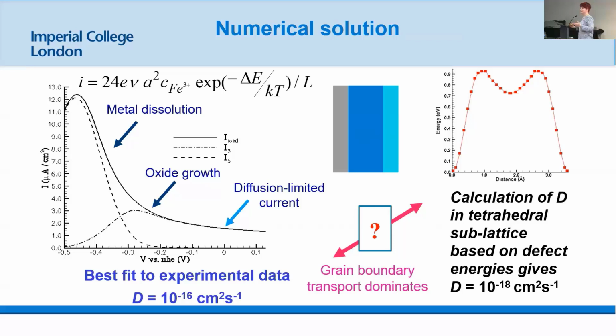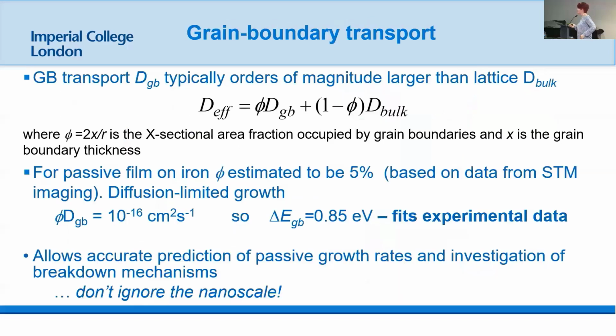So what that is telling us, actually, is that in the growth of these passive films, at least on iron and ferrous alloys, the current density in the passive state, the growth rate, is massively dependent on the grain boundaries. Right? Grain boundary transport, which you can then, this is a little bit more hand-wavy, but you can extract from the images the percentage of areas that contribute to those grain boundaries. And when you then fit diffusion through the grain boundaries, you come up with something much, much closer to that experimental approach.